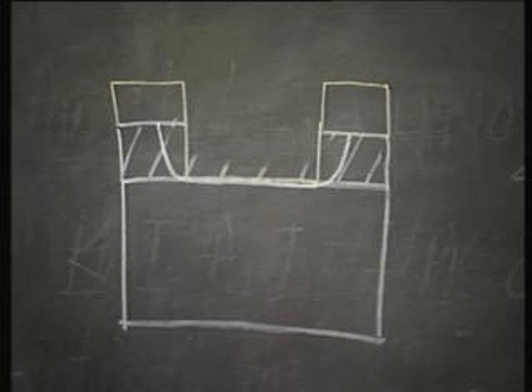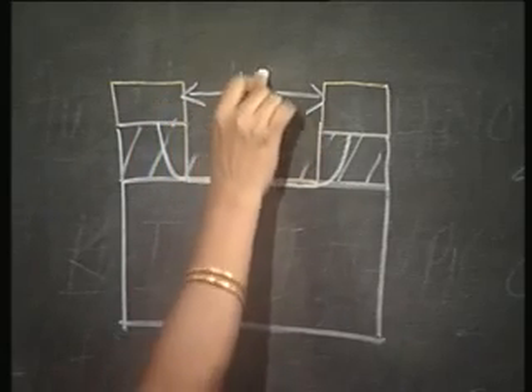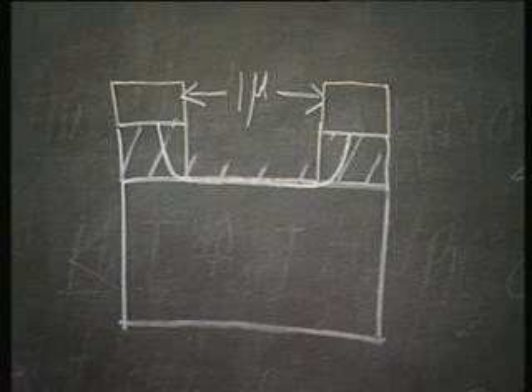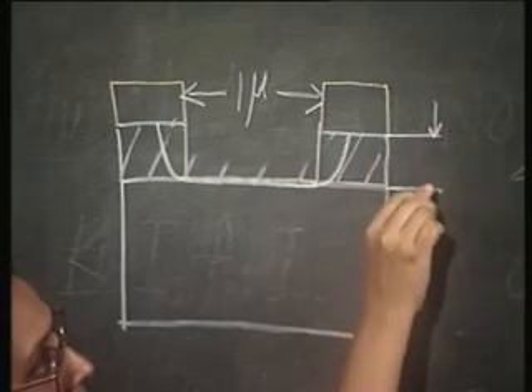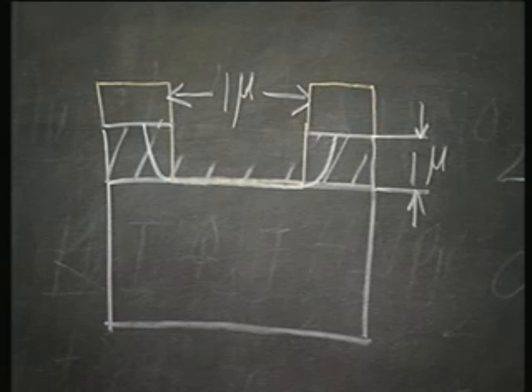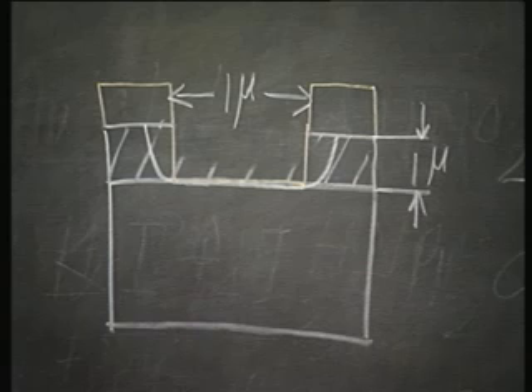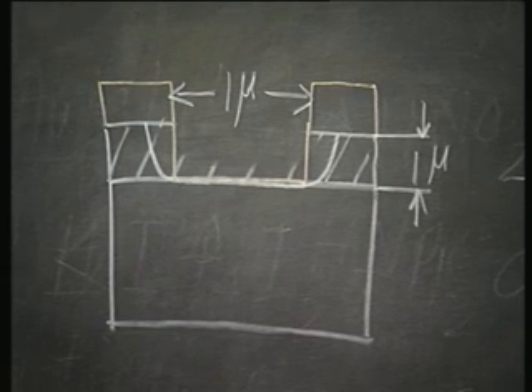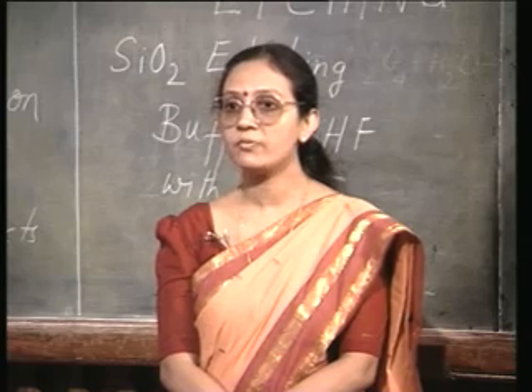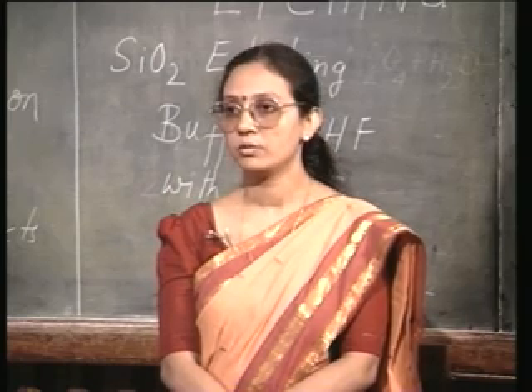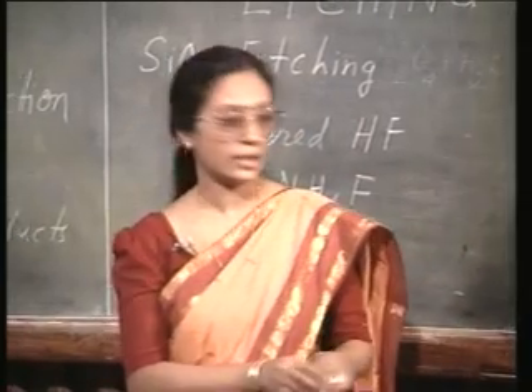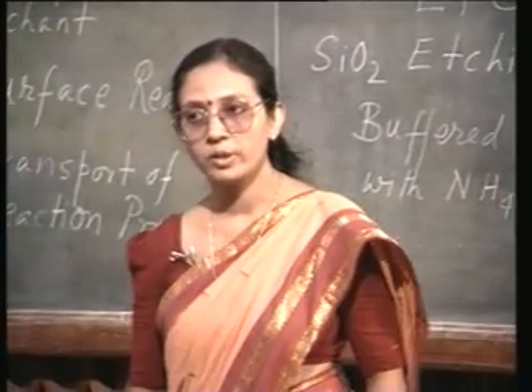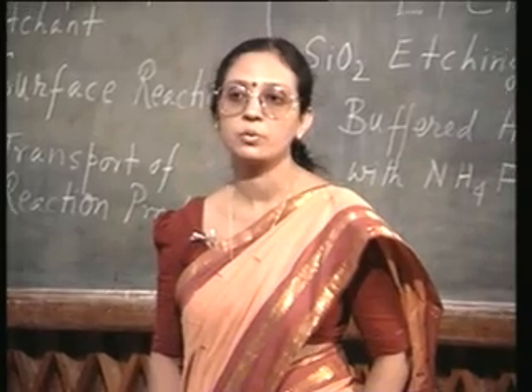Now, because the device dimensions are shrinking, if my window is 1 micron and if the height of this is also 1 micron, and if I consider that the etching is perfectly isotropic, that is, it cannot at all distinguish between the vertical and the horizontal walls, that is, the etching in the vertical as well as the horizontal direction is identical, then even though I have a 1 micron window, my final feature size is going to be 3 micron, which is intolerable. I cannot have such a tolerance. What do I do? This is the question we are going to take up in the next class.